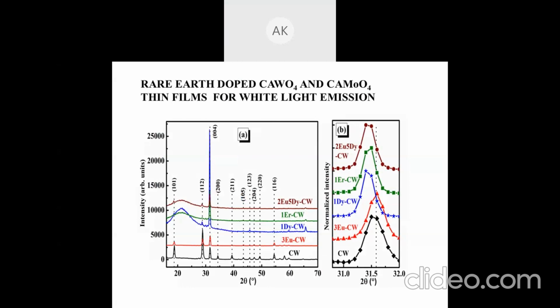And excimer laser lases in the UV region at a wavelength of about 250 nanometers. So the pulse width is only a few nanoseconds or even less. So very large energy is given to the target in a very short time, and whatever is there in the target ablates out, and the vapors are condensed on the substrates, and you get thin film deposition. So we prepared thin films of calcium tungstate and calcium molybdate, doped with rare earth ions, on quartz substrates.